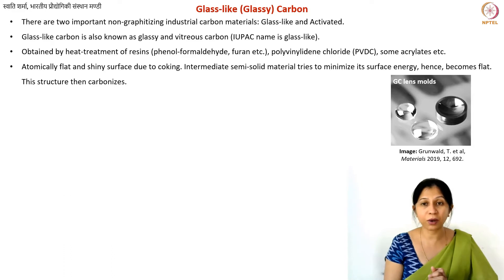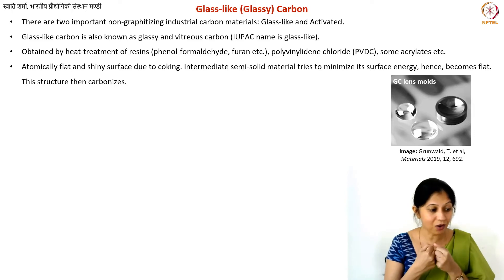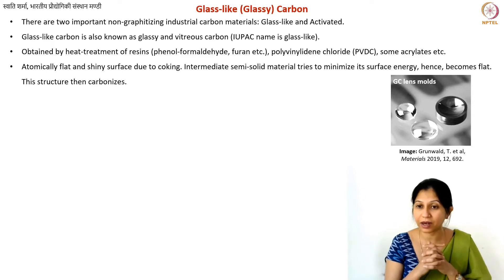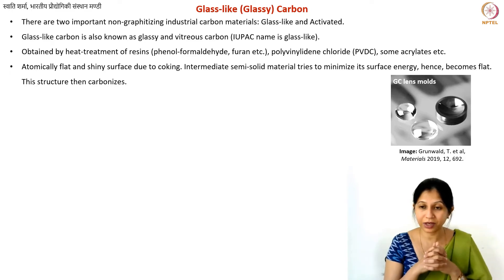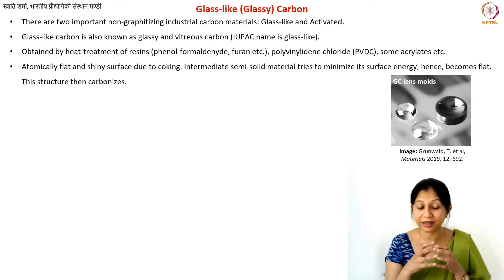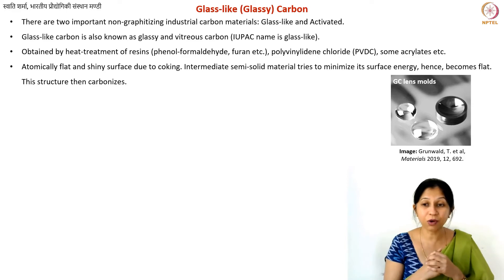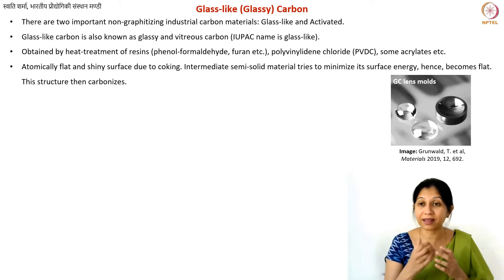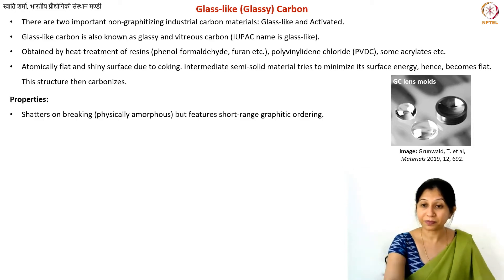Here I have also shown a picture where you're making molds for molding of glass. Glass is molded at reasonably high temperatures — 800 degrees or more, depending on the quality and type of the glass. For molding glass, you need a material that can withstand high temperatures without any distortion, and you also want a very flat surface. Glass molding has actually been one of the very important industrial applications of glassy carbon.